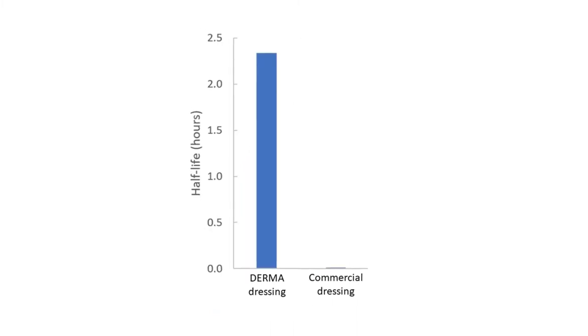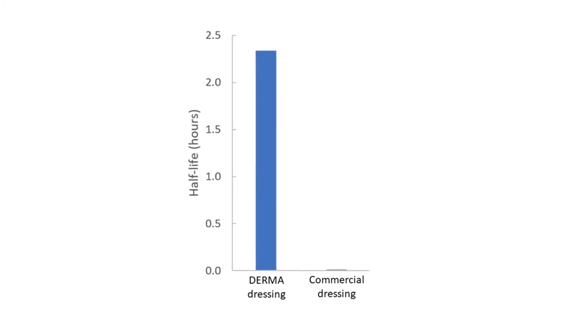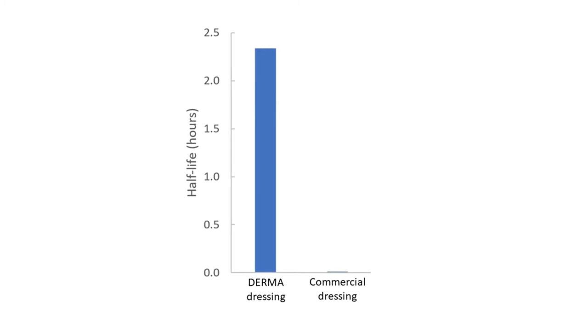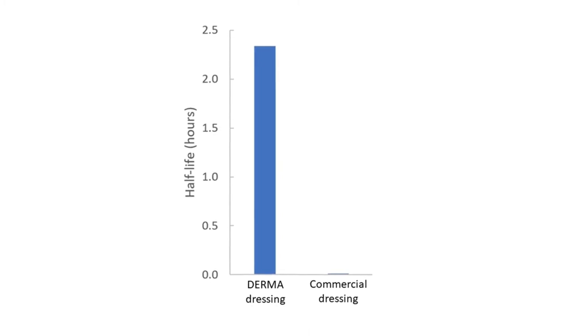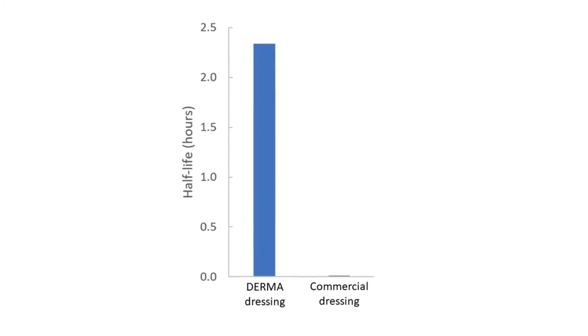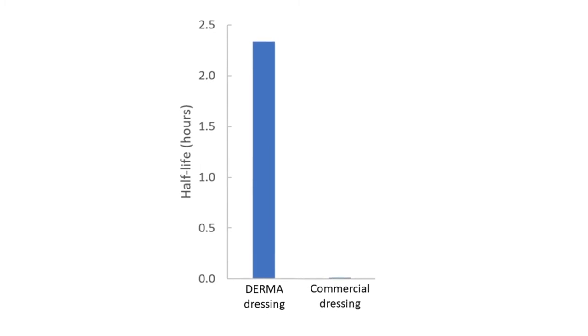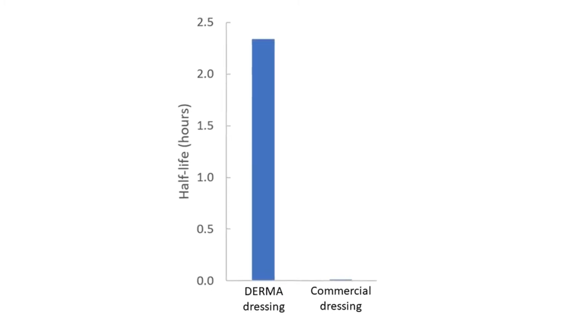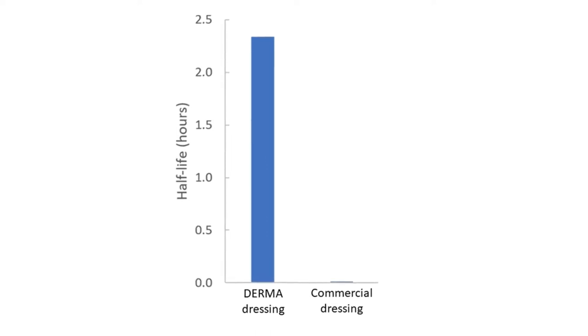So this means that the DERMA dressing will have a more prolonged effect on the wound in terms of antibacterial properties. In this figure, we can see the comparison between a DERMA dressing and the commercial dressing in terms of half-life. So what is half-life? Half-life means the time that is needed to get half of the iodine concentration leached out. We can see that for a commercial dressing, it only takes 10 minutes before half of the iodine is released into the environment. Whereas for our dressing, it takes about 2.5 hours to get to half of the concentration of iodine, which means it's a slower release of iodine in the wound.